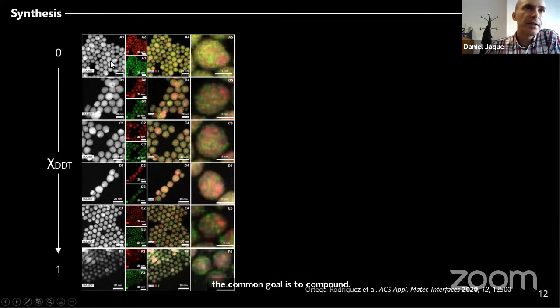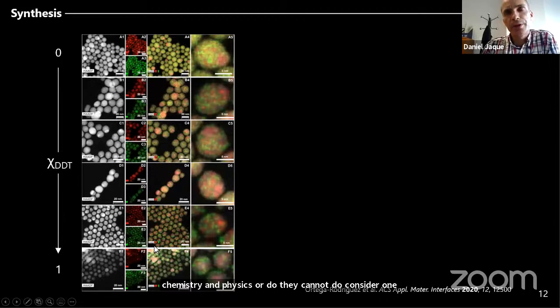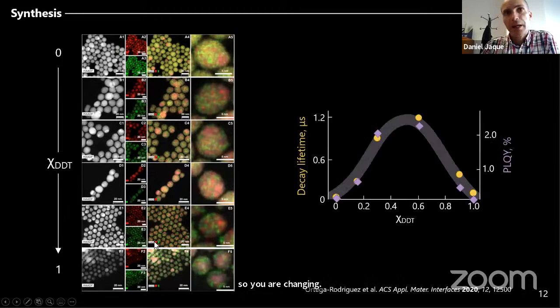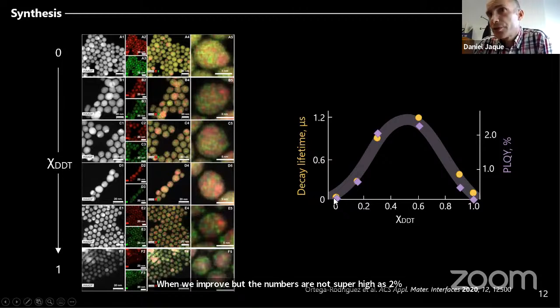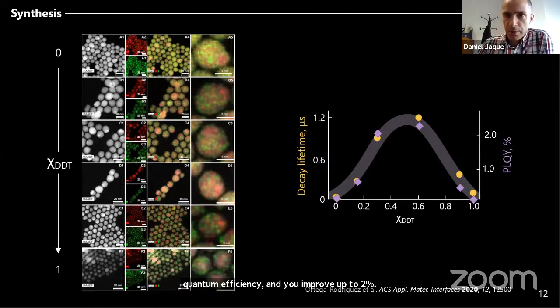Here you have the TEM image and the compositional image of the silver sulfide nanoparticles. When you change the concentration of dodecanethiol from 0 to 1, you are tuning the conditions in which you are synthesizing the nanoparticles. And these are the results. When you plot the quantum yield, it is clear that you can improve it by changing the composition of the reactor. So this is one way to improve, but the numbers are not super high. It's 2%. We started from 0.01% quantum efficiency, and you improve up to 2%. It's not too bad, but it's not enough.